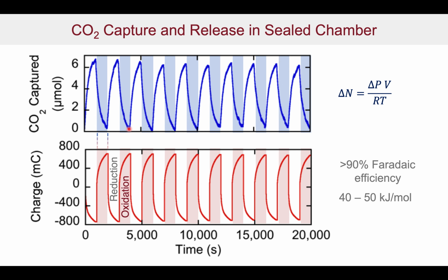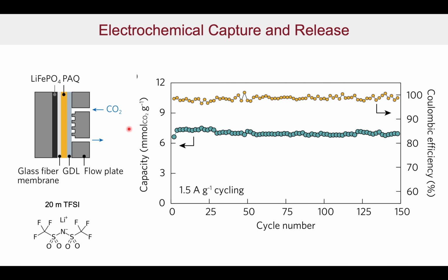We can do this, and we've done this for many, many cycles, typically with about 90% Faradaic efficiency and a typical 40 to 50 kilojoules per mole of overall energetics, which are quite favorable, actually. We can do better than that, though.